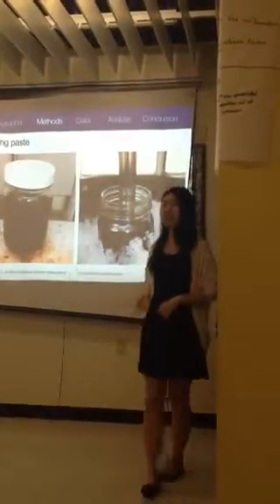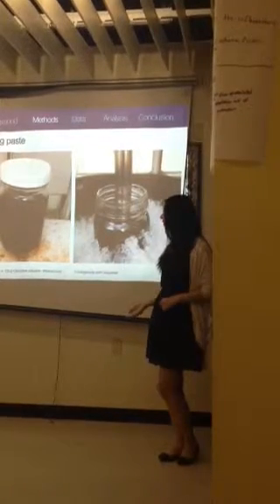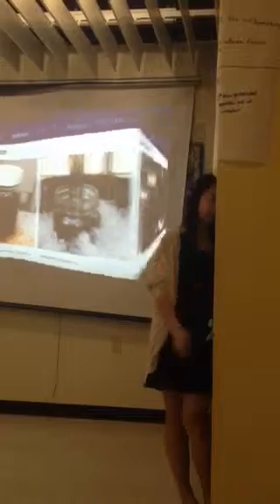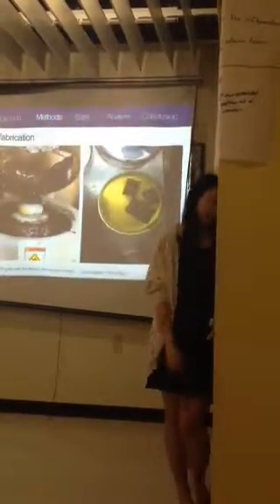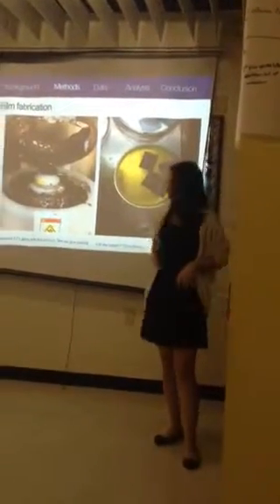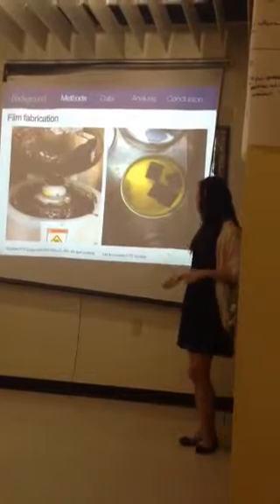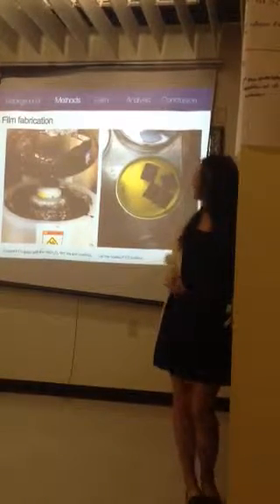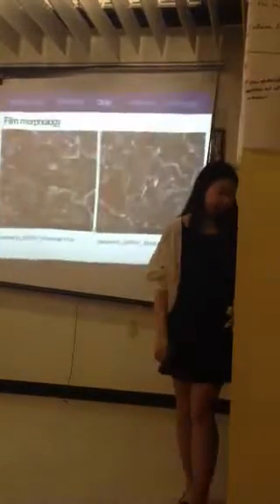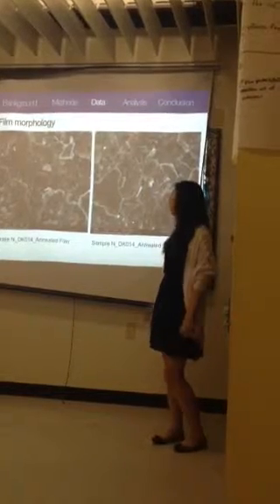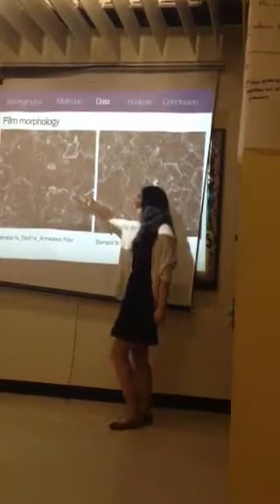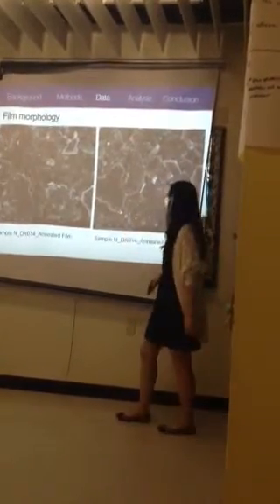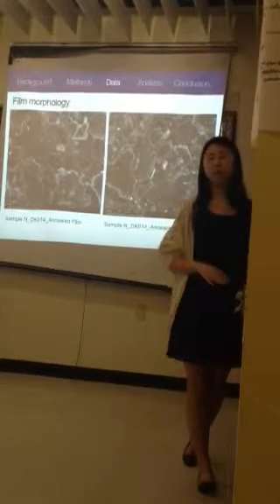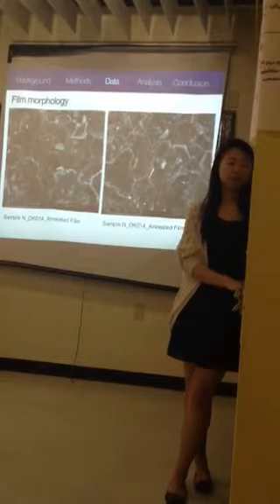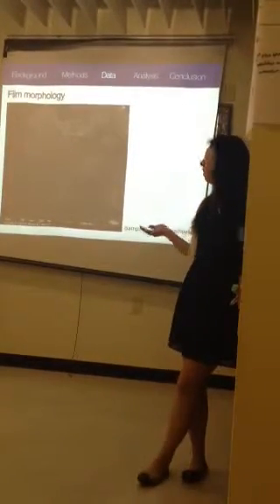After that, I made a paste in order to test the device. I added this powder into an ethyl solution and homogenized it with a disperser and an ultrasonicator, then placed FTO glass in the spin coater and coated it. The coated FTO surface sat in the dye for 24 hours so that the dye could be absorbed into the film surface. This is the film morphology I observed, and it shows the platelet shape survived. Some of them are crushed, but it's very even throughout the surface. So the film is coated really well, and all the characteristics are still there. This also shows there's porosity in the film, so all the benefits are still alive.